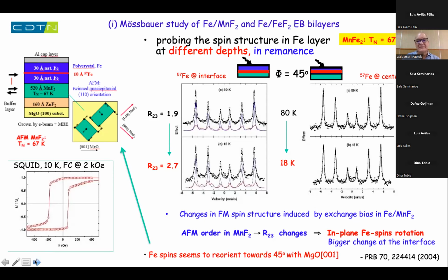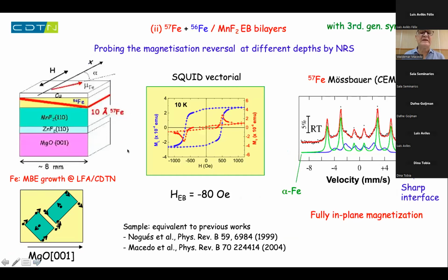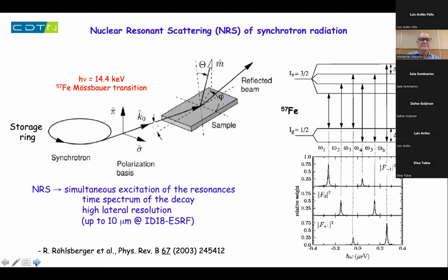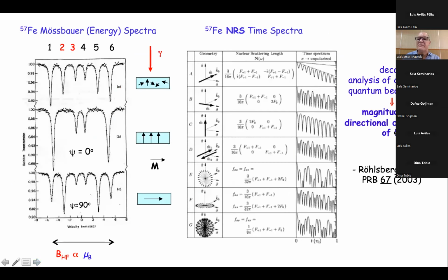And another thing: after that we got beam time at the synchrotron in Grenoble, on the Mössbauer beamline, for doing nuclear resonance scattering, and we prepared a sample like this with just one layer of iron 57 in the same systems, and that means you again have fully in-plane magnetization. The samples have a very sharp interface. With nuclear resonance scattering, as with Mössbauer, you do the measurements in the time domain, but from the spectra you can get the same information regarding the orientation of the iron spins.